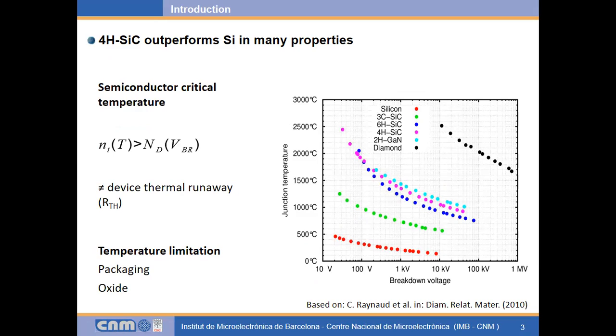But there are other aspects, such as the semiconductor critical temperature. In this case, if the intrinsic concentration becomes higher than the doping concentration, there is a risk of thermal runaway. In the picture, we can see, in other terms, the capacity to block a voltage with respect to the junction temperature. Here we can see that for 1 kilovolt, for example, silicon can block this voltage at around 200 Celsius, where silicon carbide could be capable to block the same voltage, 1 kilovolt, at around 1,300 Celsius.